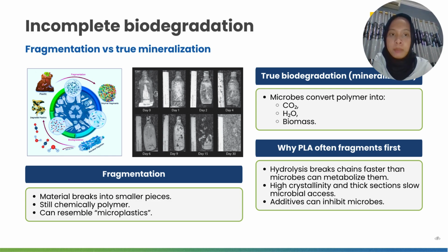Next is incomplete biodegradation, which is fragmentation versus true mineralization. Fragmentation itself is the material breaking into smaller pieces, still chemically polymer, and can resemble microplastics. True biodegradation, or mineralization, is microbes converting the polymer into CO2, H2O, or hydrogen, carbon, and biomass. Why does PLA often fragment first? Because hydrolysis breaks chains faster than microbes can metabolize them, high crystallinity and thick sections slow microbial access, and additives can inhibit the microbes.